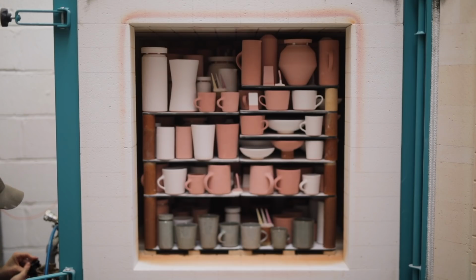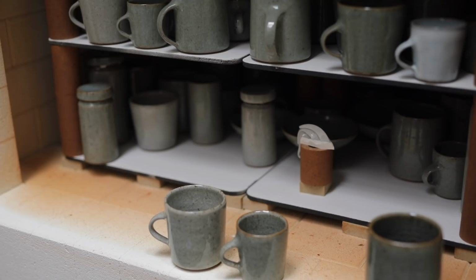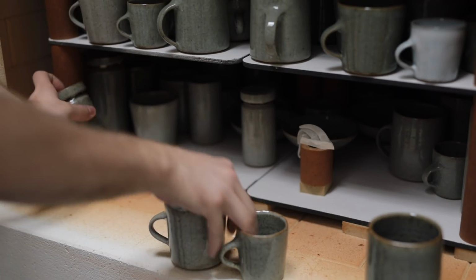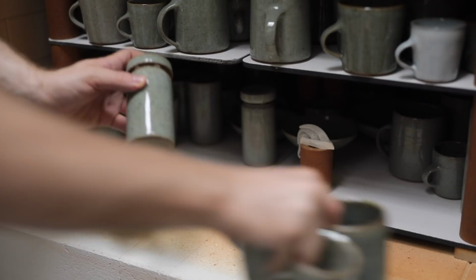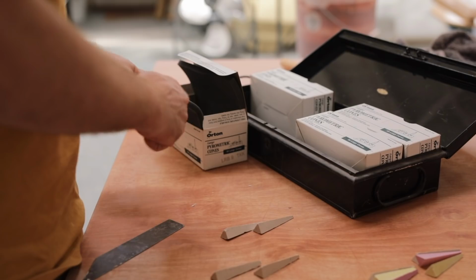They measure heat work, which is heat over time, as opposed to just straight up temperature. And as certain temperatures are reached, the cones begin to slowly bend and melt over, like you can see here. And it's by looking at these that you can indicate at what stage the firing is at. So I know that when cone 10 is flat, which is the cone on the right of the trio, it's time to end the firing.